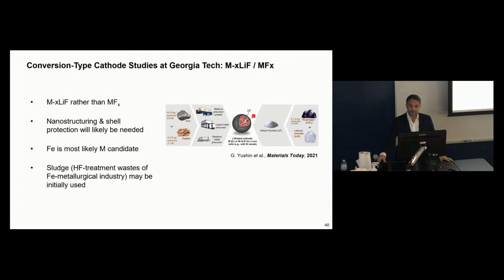And again, if you look at it more broadly, you probably need to use a lithiated version of the material to be used in lithium-ion batteries. And again, you have to nanostructure it. You have to protect it with shells. You have to nanoconfine the particles. And probably you're going to use iron as the metal in metal fluorides, because iron is very cheap, very inexpensive, and you can have very high capacity, both gravimetric and volumetric capacity, of these materials.